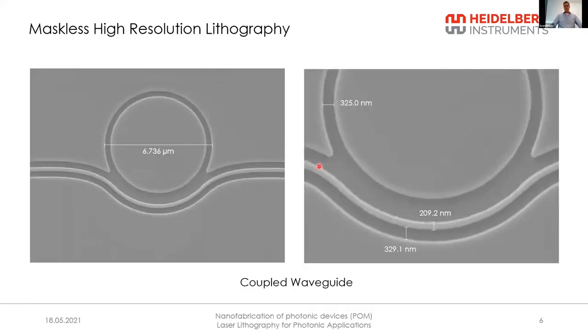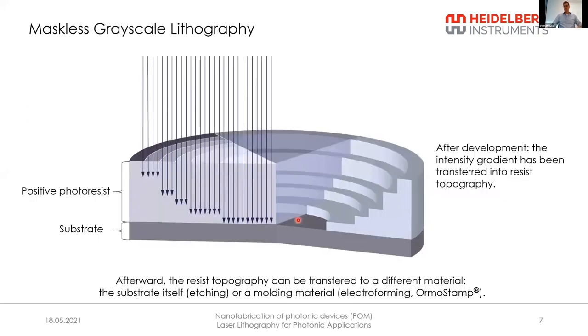This is another example of a coupled waveguide, also a few microns across. You can see here that it's also in the range of 300 nanometers, very uniform. And you can also see that it's even possible to achieve slightly smaller structures in this resist feature that remains basically between two lines that we wrote with this system. So it's even possible to go below the 300 nanometers in some cases if the process is stable. For this kind of resolution, you would usually need either a stepper and a high resolution photomask or an E-beam writer to achieve this. And this laser system offers a much faster and easier way to achieve this resolution.